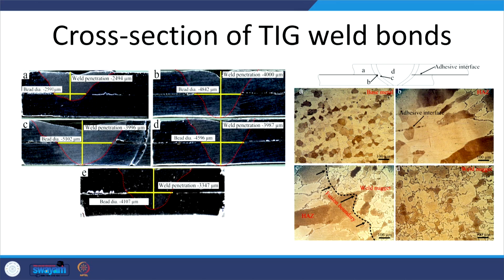Okay. When we see the cross section, if we use less heat, then the melting of the lower sheet is limited, but melting of the top sheet takes place completely. If we use a higher heat input, then complete melting of even the second sheet takes place. This is the zone where the metallurgical bond across the sheets will be developed. In other areas, we may have the adhesive bond working. This is the case where partial penetration of the lower sheet has taken place. Because heat has been supplied in good quantity in order to realize the melting of the top sheet as well as part melting of the lower sheet, it generates the heat affected zone and the fusion zone also.